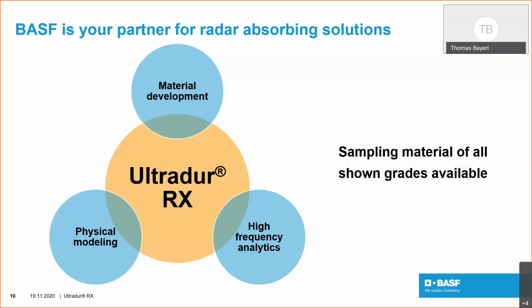So then I received another question or statement: very good performance at 79 gigahertz. How is the performance over frequency from 76 to 81 gigahertz? Yeah, I can answer this. There is no significant frequency dependence in this automotive frequency range, meaning the dielectric parameters are more or less frequency independent, and also the scattering parameters are more or less frequency independent. There are only very slight changes in the range of a few percent. Okay, thank you.